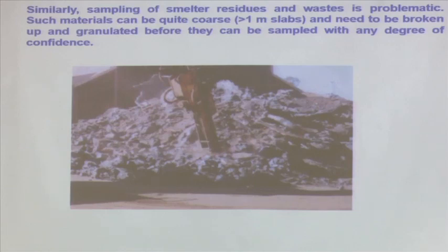So, the best way of doing that is, when the blast furnace slag heap is being formed or being dismantled, at that time you should take the representative samples from a moving stream, based on Gy's formula for how much sample I should take. Then you further grind it and come to the laboratory, and you use some other laboratory sampling techniques to get the samples. You cannot do that otherwise. Okay.